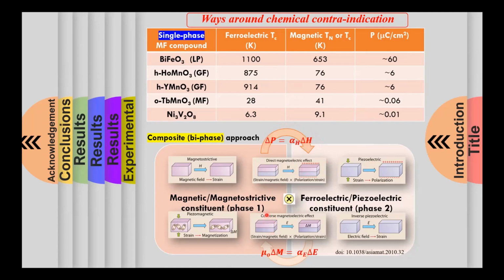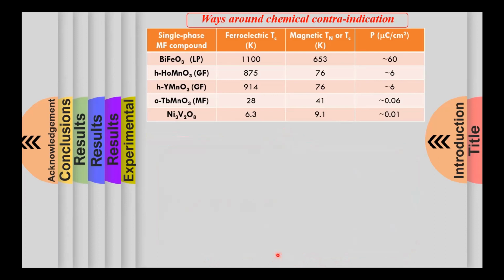On the other hand, in the converse magnetoelectric effect, an electric field is applied such that the piezoelectric phase undergoes a strain, it undergoes a deformation, and this strain is transferred onto the magnetic phase and magnetization is induced. And this is the governing relation, that is, the electric field is inducing the magnetization. Now, since this coupling is via strain between the interfaces of the two constituents, therefore, an intimate contact between the magnetic and piezoelectric phase must be maintained.